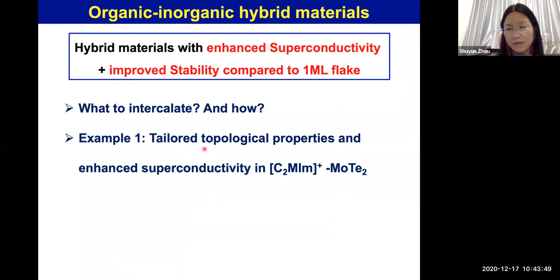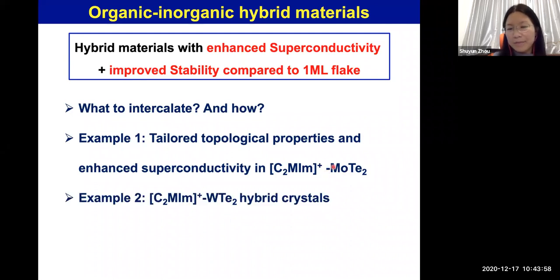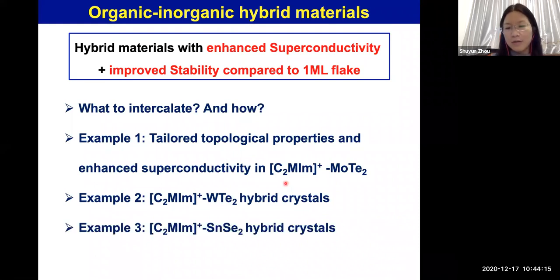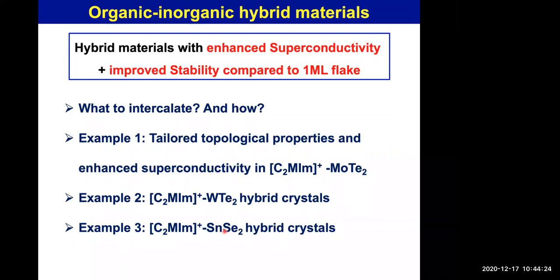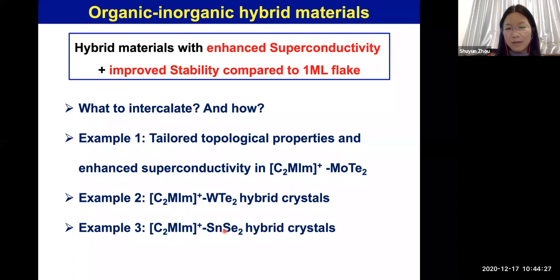First of all, these are tailored topological property and enhanced superconductivity in intercalated molybdenum ditelluride. And similarly, this method can also apply to tungsten ditelluride, but with a TC much higher compared to the monolayer flake. And so these 2 materials are topological semimetals. We find that for other layered materials, say semiconducting tin diselenide, we can also induce superconductivity to make this semiconductor-to-superconductor transition.